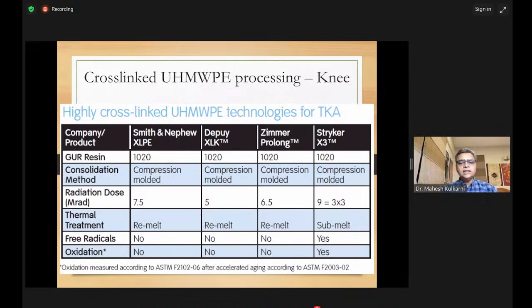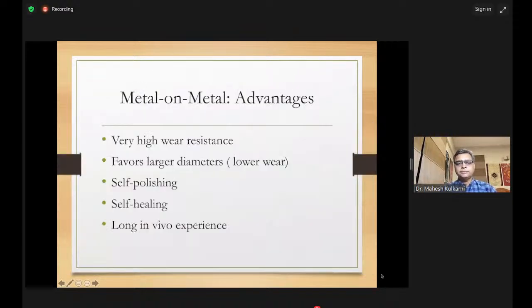And these are the knees. For the knee, another variable is whether the polyethylene comes out as a compression molded poly, but most of them are now, as you can see, compression molded poly. And the Stryker one, again, is a submelted or annealed poly, 3 times 3 megarad. The DePuy XLK is 5 megarad. The Smith & Nephew XLPE for knees is 7.5 megarad. And we now know which will have residual free radicals and which won't. So that was about polyethylene altogether.